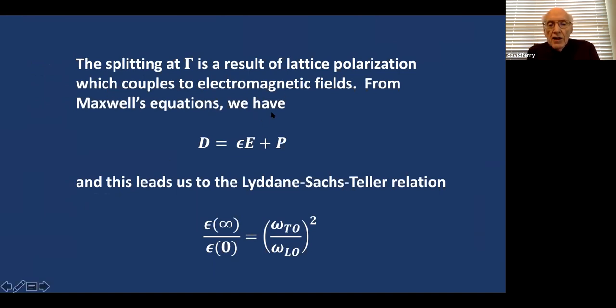Now, electrical engineers know about Maxwell's equations. D is the electric flux density. Epsilon is the optical dielectric constant in the material. This is the electric field intensity. This is the polarization. Now, if we say the polarization is linear in the electric field, which it isn't always, but if we say it is, then we can write this as a susceptibility times epsilon. And 1 plus that susceptibility gives you a contribution to the dielectric constant, which separates the 0 frequency static dielectric constant from the optical dielectric constant. So the 0 frequency is a higher dielectric constant because it has a polarization in it.